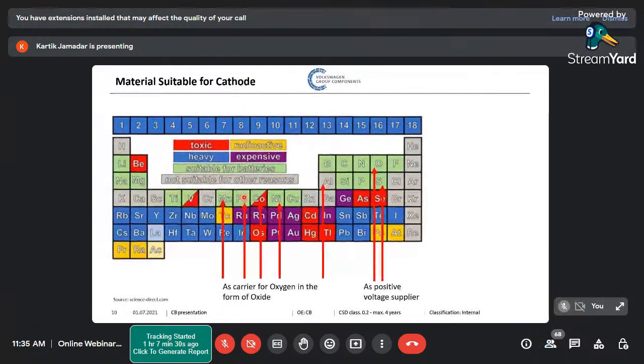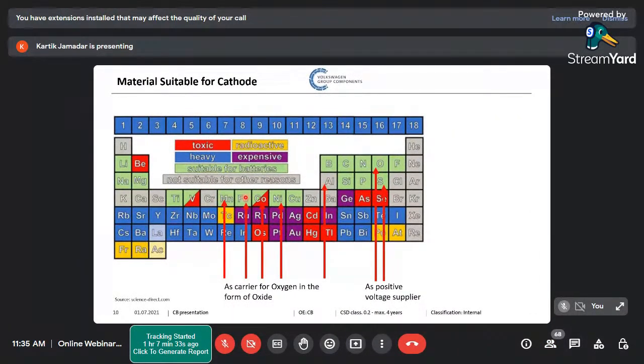There is another trend going on in the same direction. At least for the Indian market, I feel it's very important if we could use cobalt-free, nickel-free material, because the cost is very important. And there comes iron phosphate, LFP. Iron phosphate has the advantage that it is very stable. It does not explode. It is a very safe cell, but it has an energy density which is half that of the NMC cell. So you will have to compromise on the energy density, and it can give a maximum of around 3.3 volt. Normally we can get around 4.2 volt for an NMC cell, and for LFP only up to 3.3 volt.